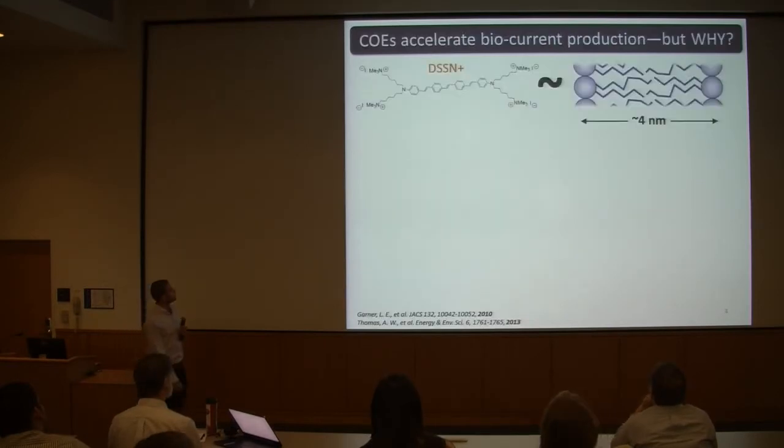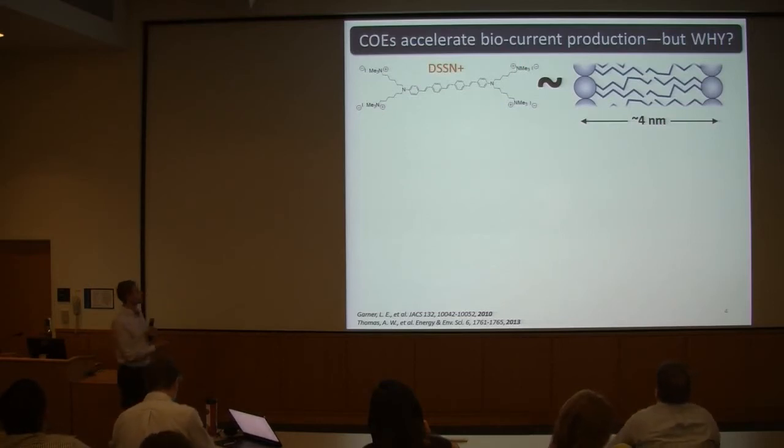So first of all, I have to introduce you to this class of molecules. Conjugated oligoelectrolytes bear a pi delocalized hydrophobic core, which is semiconducting and fluorescent. And there are polar pendant groups that impart water solubility. What's important about these molecules, though, is that their amphiphilic structure mimics the amphiphilic structure of the lipid bilayer. And so they will spontaneously intercalate into the membrane from an aqueous environment. So they'll partition into the membrane with a pretty strong affinity. Now this is powerful because presumably we're now introducing a semiconducting moiety into a rather insulating structure.